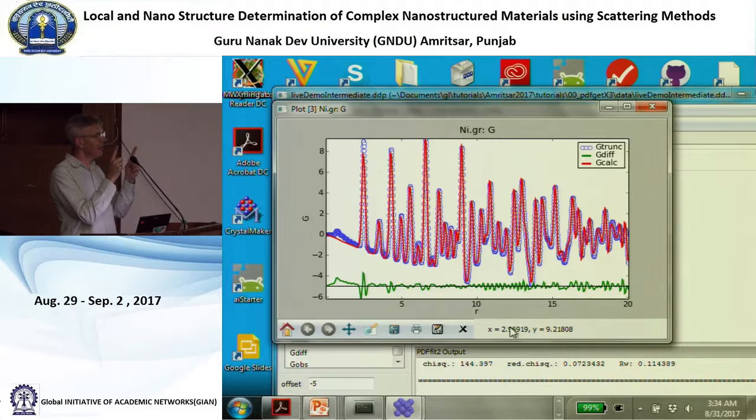If the atom on the left moves to the right, it's strongly bonded to its neighbor, so it actually pushes the other atom over. So these atoms can be undergoing large amplitude motion, but because they're directly bonded to each other, the PDF peak will be very, very sharp, because when this one moves to the right, the other one moves to the right. It's correlated, the motion.